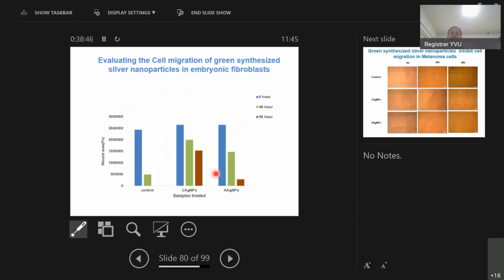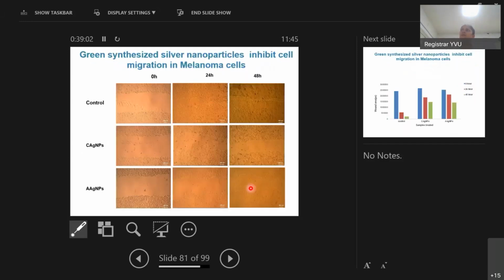These are the wound areas measured. This is the cell migration analysis in mouse embryonic fibroblasts at 0 hours, 48 hours, and 96 hours. This is the Catharanthus roseus and Azadirachta silver nanoparticles migration. After that, we analyzed the cell migration in the melanoma cell line. These are the control group and the Catharanthus roseus and Azadirachta silver nanoparticles treated melanoma cells.